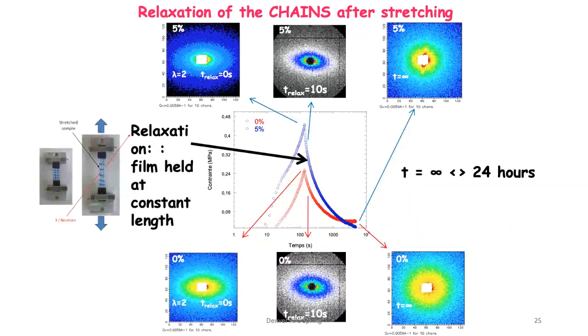And you can see that in both cases, whether it is filled or not filled, the relaxation is showing more or less the same kinetics. So of course, this is a very incomplete experiment, but it would be nice to go in this direction to actually follow the dynamics, the relaxation dynamics of the chains, comparing filled and non-filled. And I would suggest that they could be very similar.